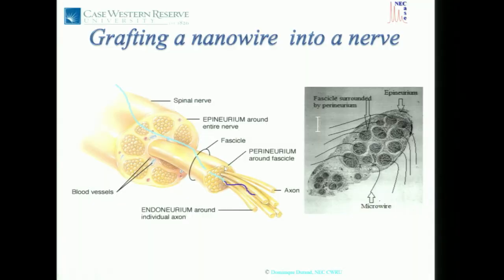Very similar. Can we just build another axon, basically, and stick it in there so that the nervous system doesn't even know it's there? That would minimize all the reaction and fibrous encapsulation possible. So you can see that here, this is the typical nerve. Recognize the axons. The fascicle here has the perineurium around it. And here's the epineurium. And so we've envisioned this wire that's really small, about 10 microns, similar to an axon, that would be finding its way through the perineurium and into the bunch of axons that are there.